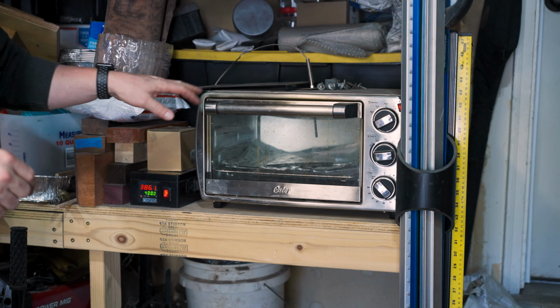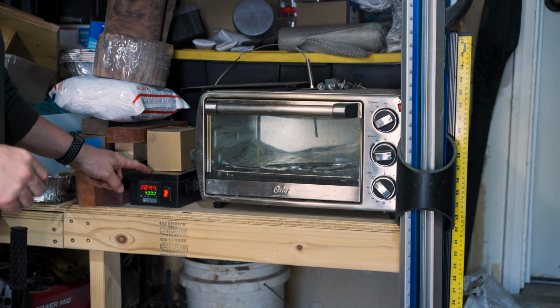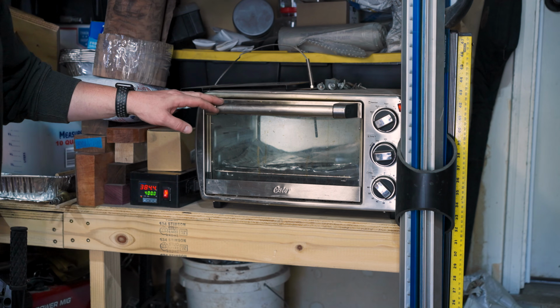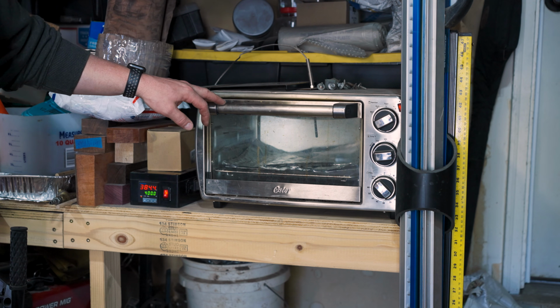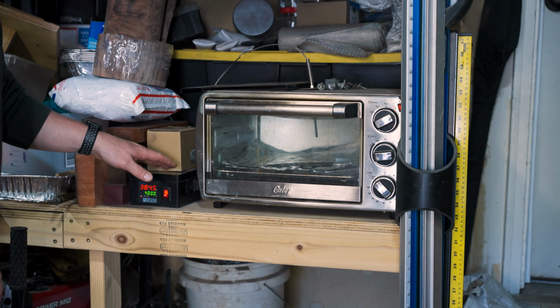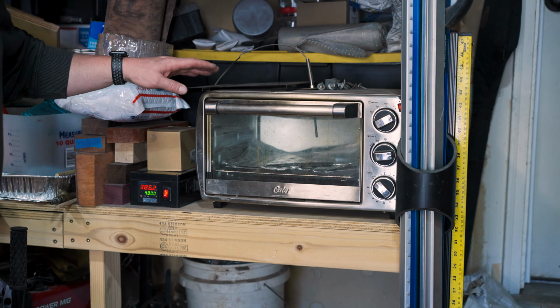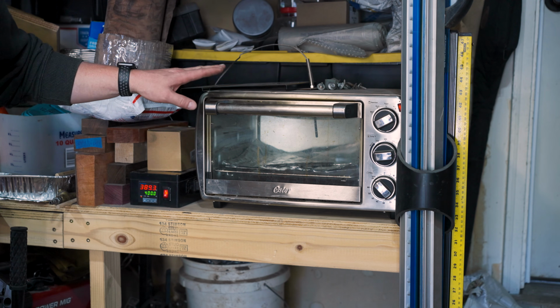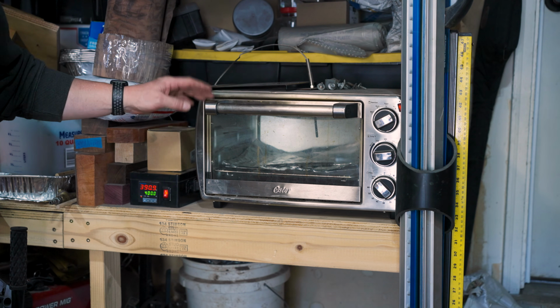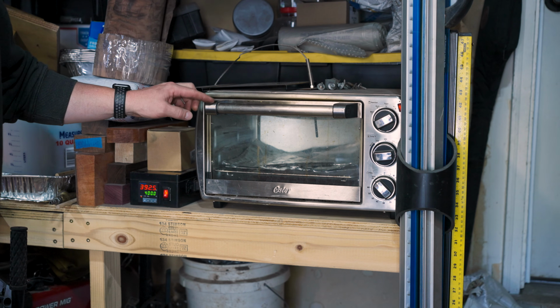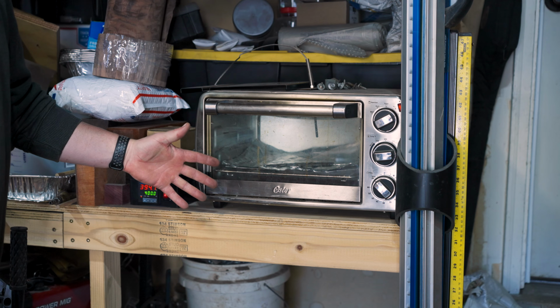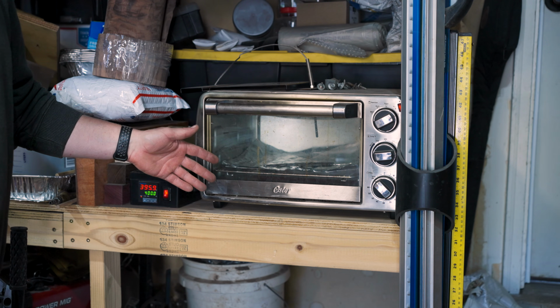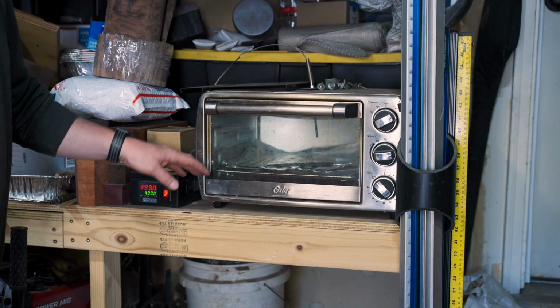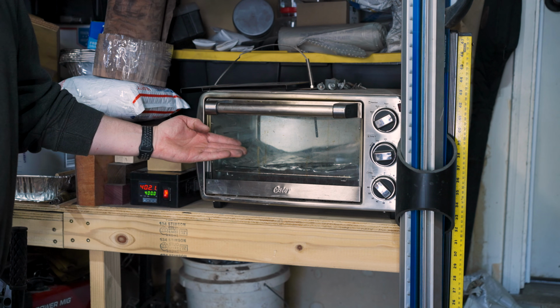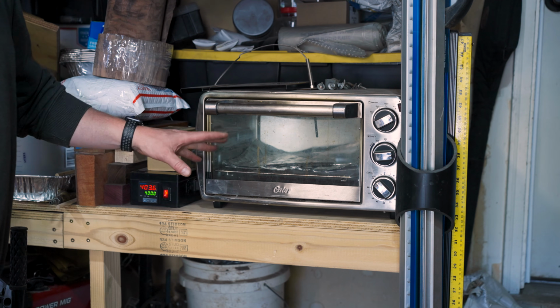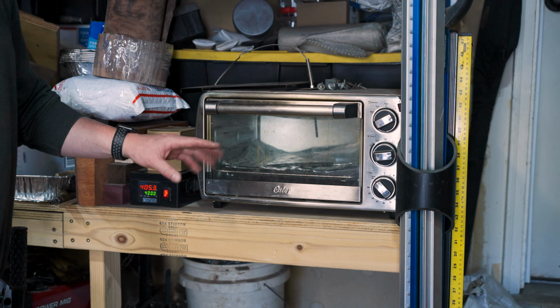Our target for tempering is 400 degrees, which according to the chart should take us to about 60 to 61 Rockwell if we've gotten the quench correct and everything. And we're going to do 2 temper cycles at 2 hours apiece. So we're going to leave this in here for 2 hours. We're going to come back, and you can either let it cool on its own to room temperature, or you can dunk it in some water. I haven't had an issue with either way. And then we're going to put it back in once it's down to room temperature and do another 2 hours. And after that, the heat treat on this blade is complete.